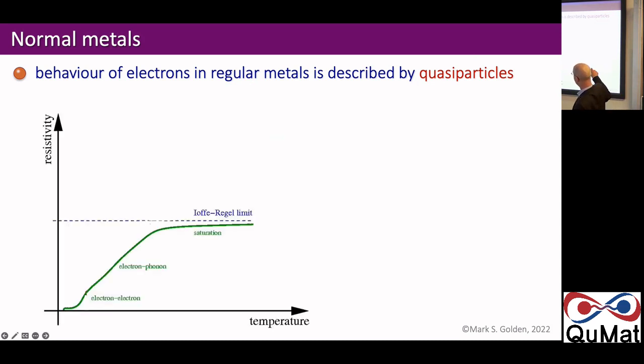So let's imagine a normal resistivity curve for a metal or superconductor versus temperature. So the resistivity, if it's a superconductor at some stage, will be 0. And then at the transition temperature, the resistivity will appear. Then you'll see some low temperature behavior where the resistivity will go as T squared because of the electron-electron interactions in the material. It's a phase-space argument to do with how electrons can scatter from below to above the Fermi surface of your metal. So even a piece of copper has this behavior. Then as the electron-phonon interactions overtake, you get something which can be quite linear. And at some stage where the mean free path length describing the scattering of these electrons gets to be of the order of the interatomic spacing, you can't get more scattering than that, and the resistivity tails over. And this is called the Ioffe-Regel limit.